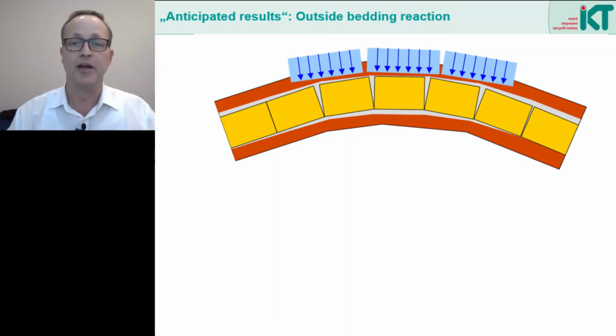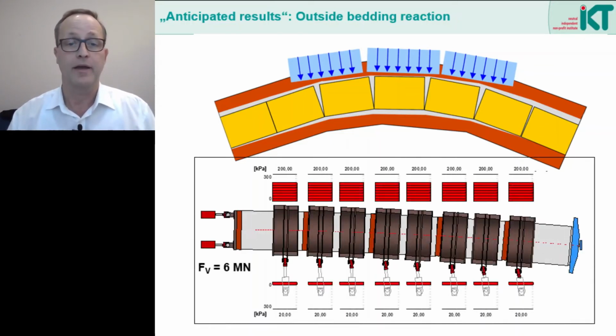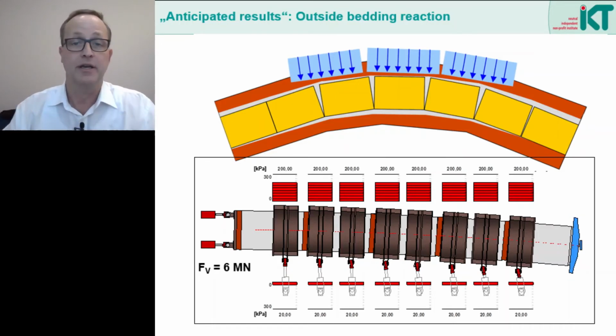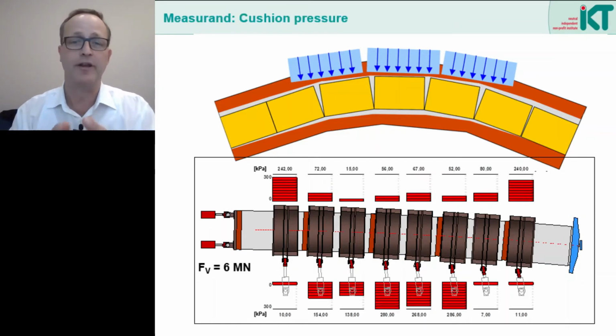But the nice thing about our experiment was that we could measure in the hydraulic cushions what really happens in the bedding. And of course, we and all the experts who accompanied the project expected the following. We expected that we would be able to measure a very even bedding reaction on the outside of the curve. Anything else would not be logical, at least we thought. Well, and then came the results. We can see very quickly that everything looks very different. The pipes are held on the outside, but this is especially true for the first and for the last pipe.